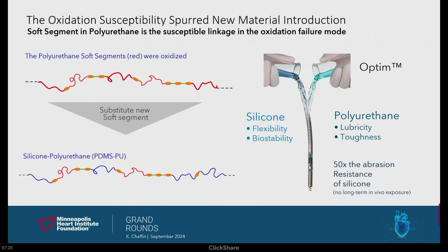I drew a cartoon to save you from the chemistry. The soft segments are the red squiggles on the line. And so if you remember from your general chemistry class, you have a reaction A plus B goes to C. One way to slow that reaction is to suppress the number of reactants, right? So if I have A plus B goes to C, and I don't give it enough B, that reaction isn't going to make as many C's. So if C is my short polymer, I now want to take away red segments, right, to turn off my oxidation reaction. And what the industry did was to substitute a new red segment.